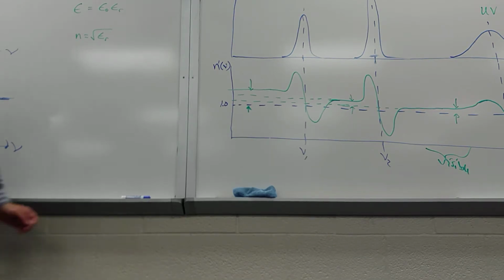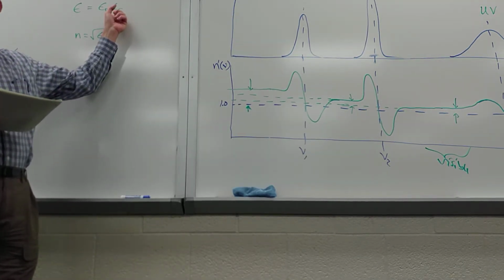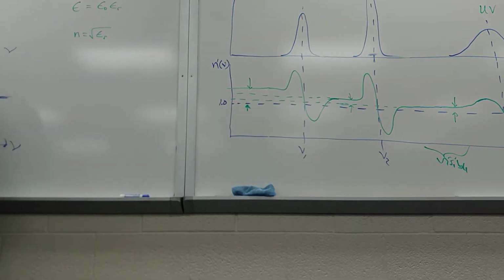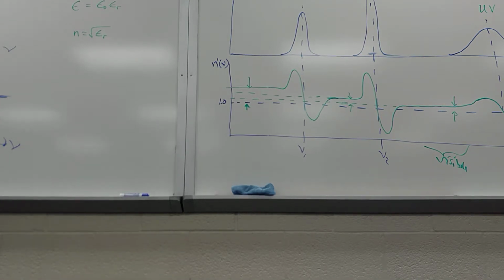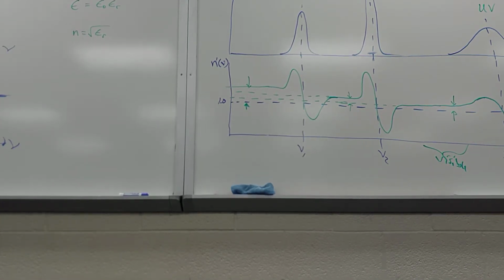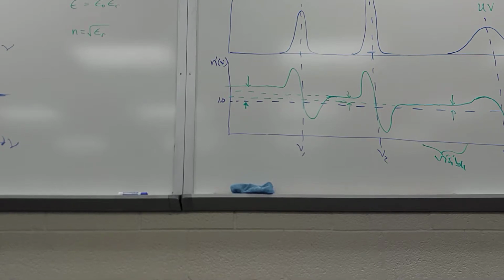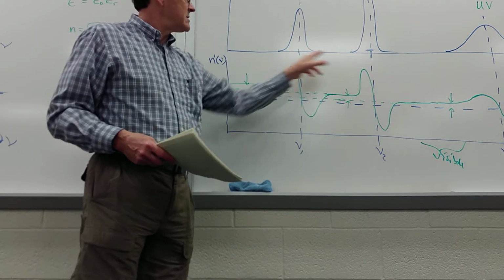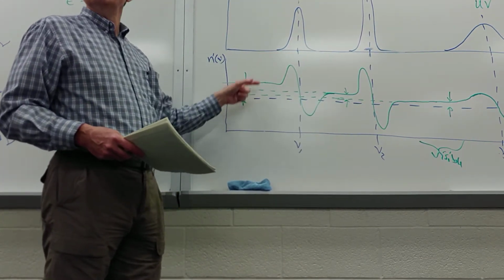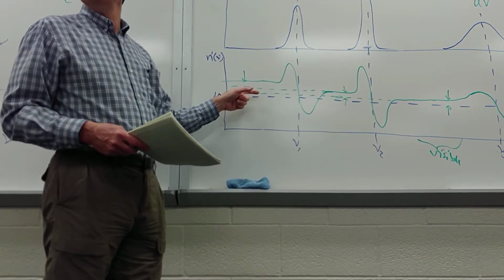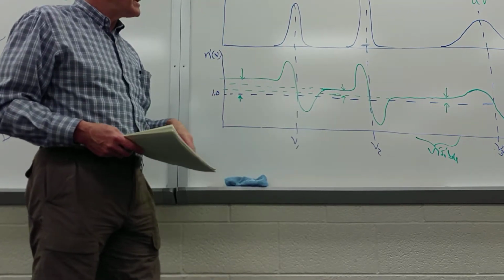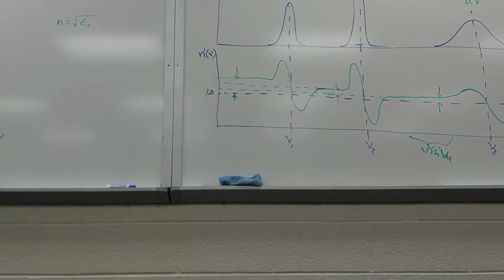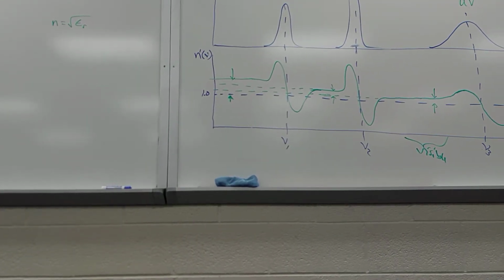And so, this dielectric constant, you typically see that for, if you're doing electronics, then you're getting the value that's good at DC, a megahertz, a gigahertz, all very low frequency stuff compared to optical frequencies. So that means you're below these absorption resonances, so you're picking up the effect of those resonances. So that's why you have to be really careful to make sure when you're looking for physical constants to pick them out in the right frequency range.